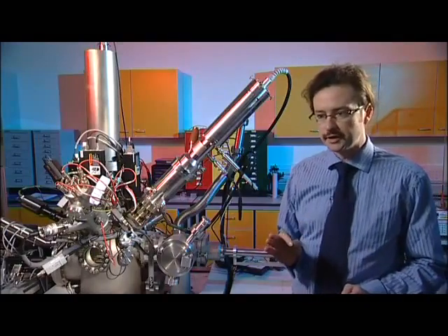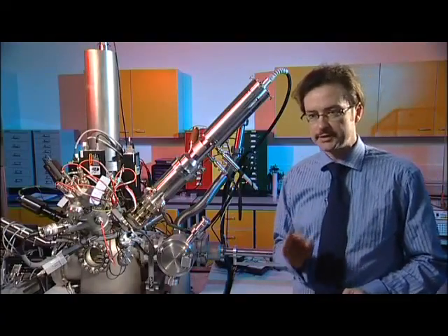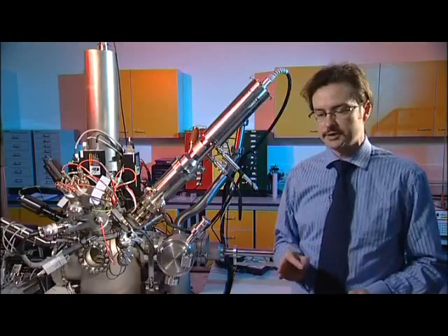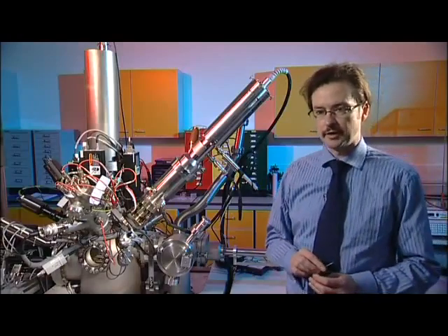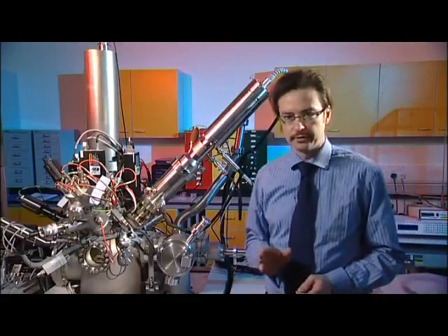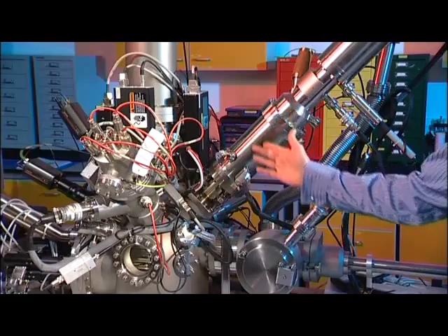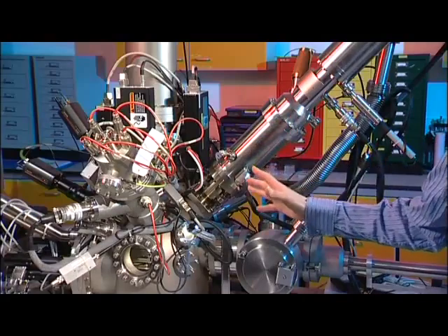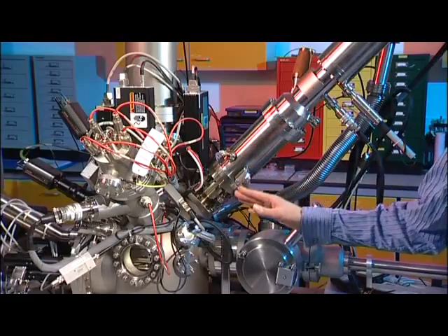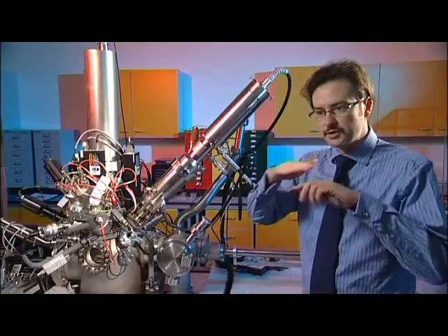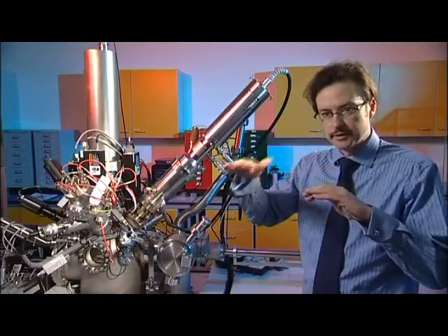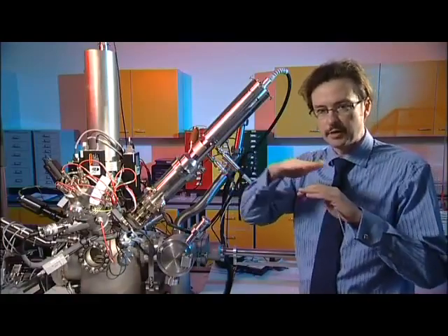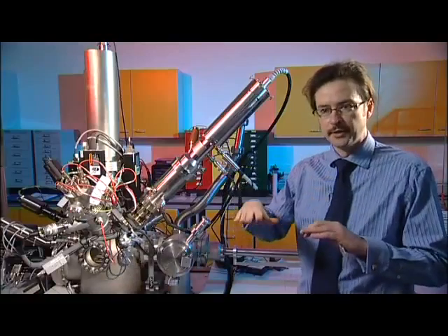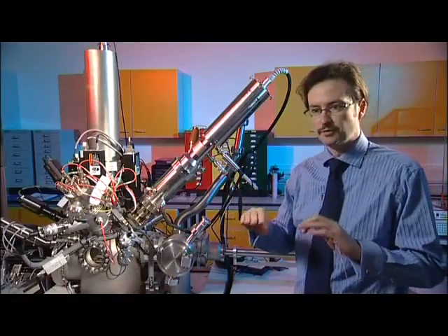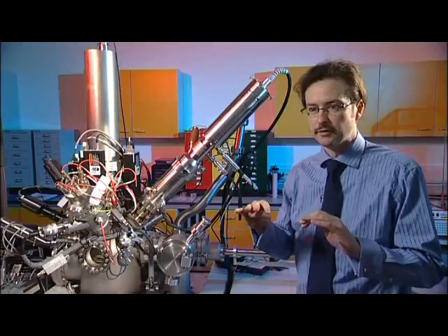And quite recently there's been a major leap forward in analytical capability with the development of cluster ion beams for organic depth profiling. And what we're able to do with these is use an ion beam like this one here. This fires C60 ions at the surface, and this allows us to gently remove the layers off the surface while providing chemical maps as we go through the material, and that then produces a 3-dimensional molecular image of the material.